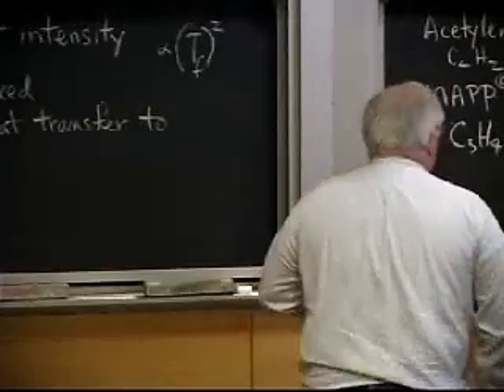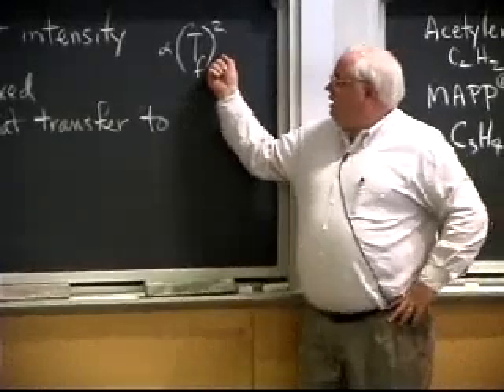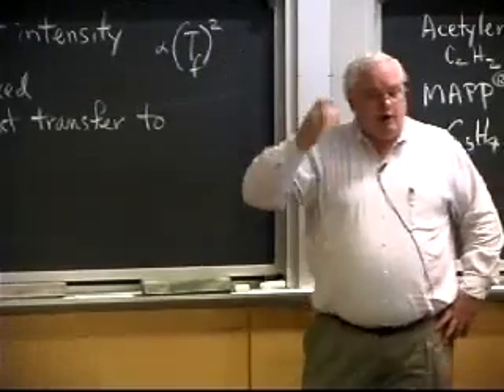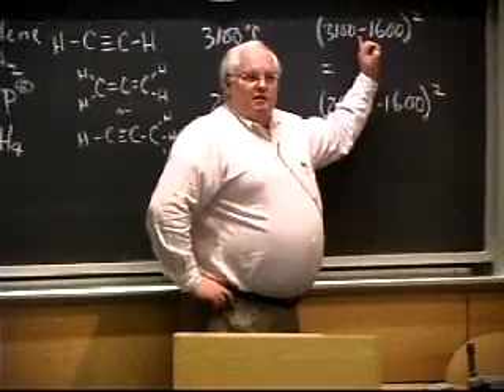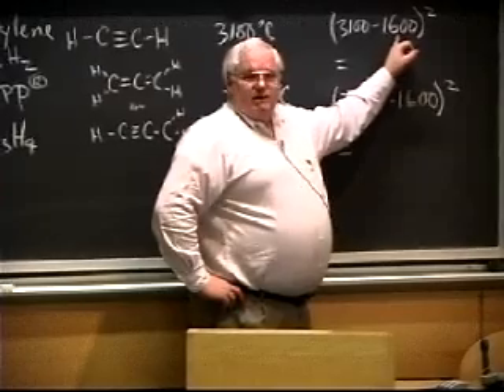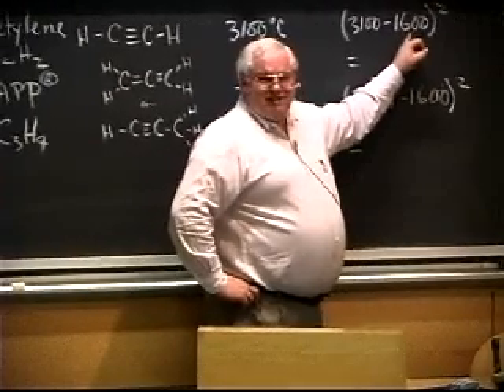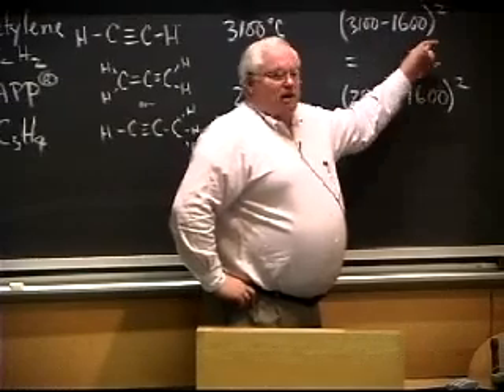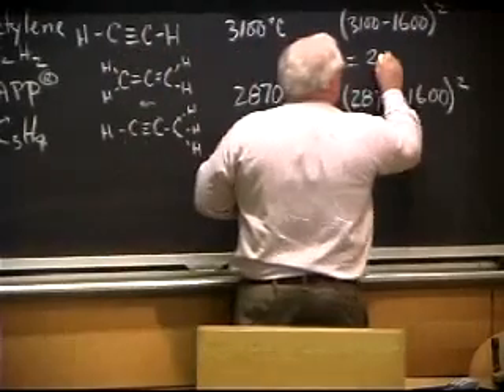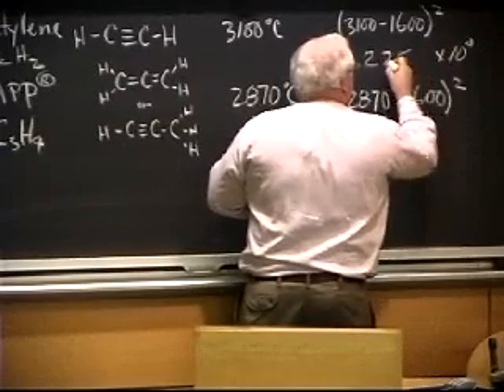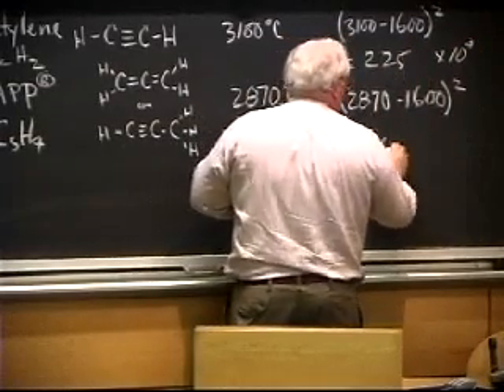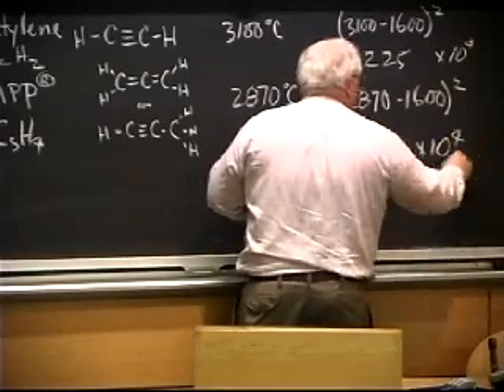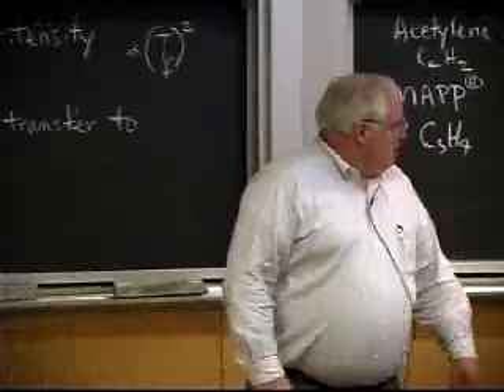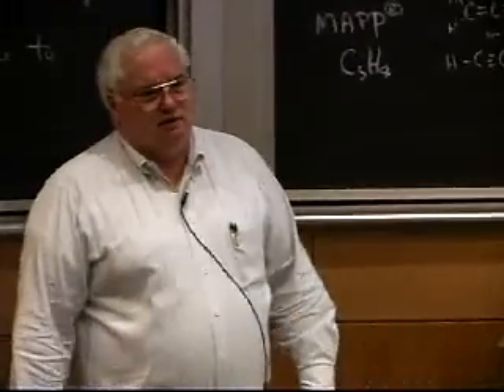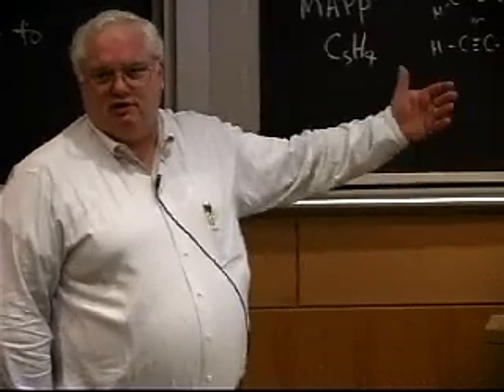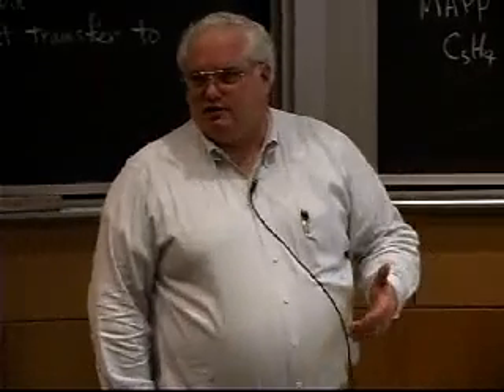Well, it turns out the heat intensity goes as the temperature of the flame squared, and if I'm trying to melt steel, the temperature difference I'm interested in is relative to the temperature of that weld pool, which is about 1,600 degrees centigrade. 3,100 minus 1,600, that quantity squared, is 225 times 10 to the 4th. 2,870 minus 1,600 has value of 161 times 10 to the 4th. So even though there's only an 8% difference in the adiabatic flame temperatures, of course that's degrees centigrade, not degrees Kelvin, but you can figure that's probably a 7% difference in degrees Kelvin or something.